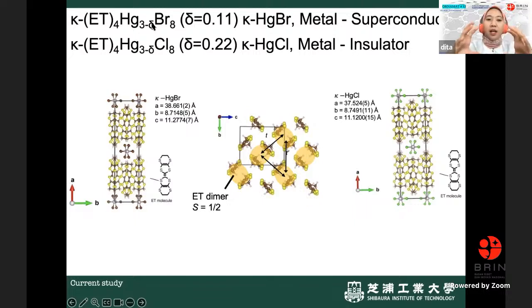So there is some incomplete stoichiometry of mercury here due to the incommensurate lattice in the crystal structure. So there is some kind of mismatch. The unit cell is repeated normally, but the mercury metal here, maybe there is a little bit of mismatch, so it cannot be perfectly 3. So it's kind of 3 minus something. So this is the doping. So it becomes a doping system. This material has doping situations, but also can be easily tuned by pressure.